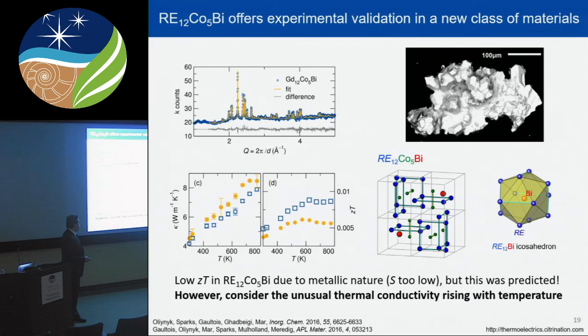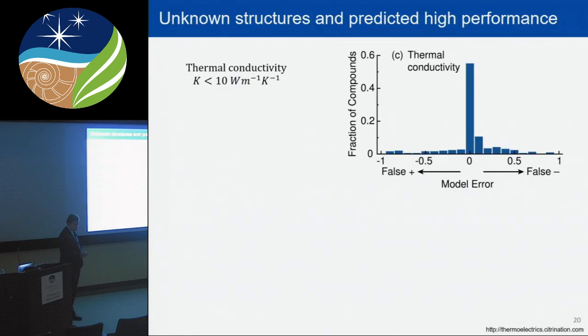The reason for low thermal conductivity is the unusual environment around the bismuth atom, which rattles in a cage. The overall structure looks very similar to the skutterudite type structure, quite common for other thermoelectric materials, but it's a little bit distorted. That's why it would simply be overlooked by chemists, because it doesn't look similar at first glance, but when we analyzed the structure, it was quite similar to the skutterudite type structure, typical for thermoelectric material applications.